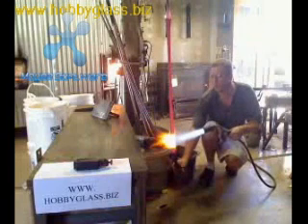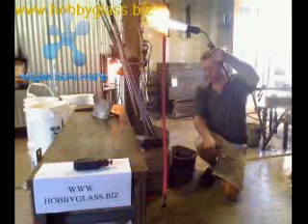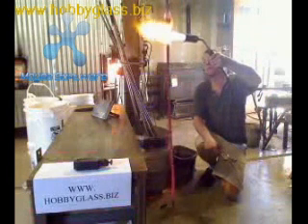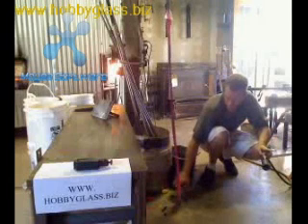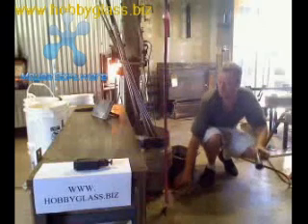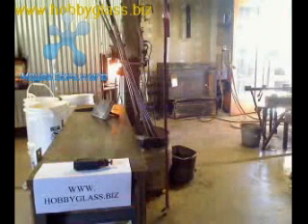A little bit of light torch work on the bottom where it's a little bit thicker usually leads to a nice pull. Ideally, you want to minimize the use of the torch, but it's a very, very helpful thing to have. You can certainly make everything without it, but your yield tends to decrease, your seconds tend to increase, obviously. There you go. That's a pretty good pull. It's just not as satisfying.